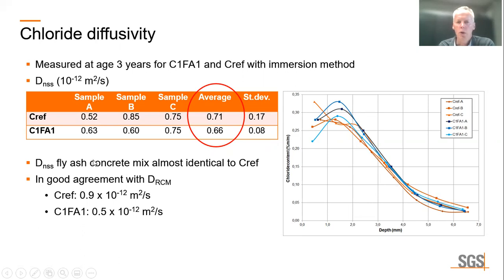So the fly ash concrete mix has an almost identical diffusivity, and these values are in fairly good agreement with those of the RCM test after 3 years, which are shown here.